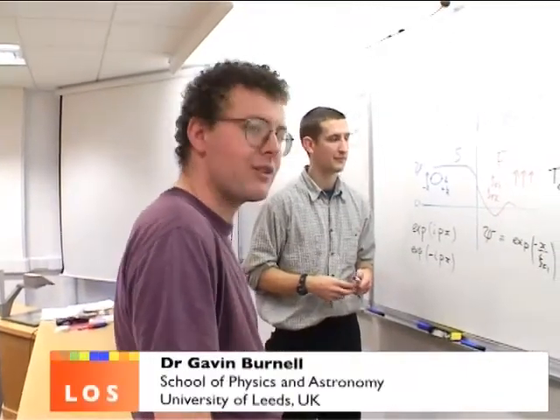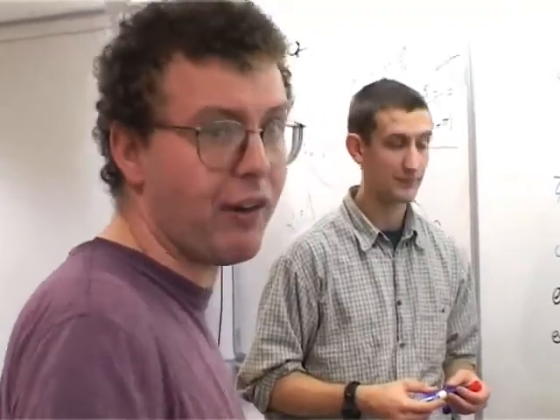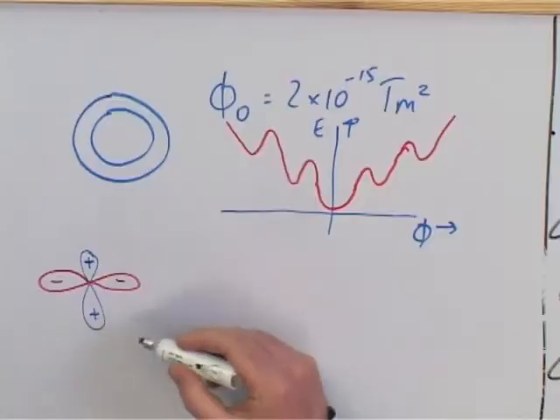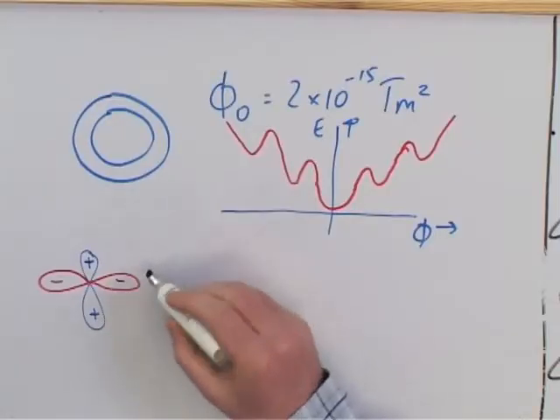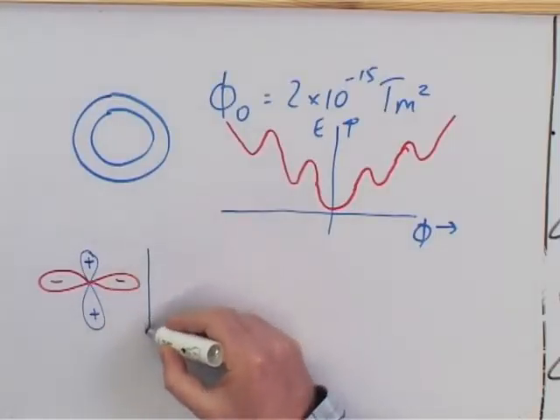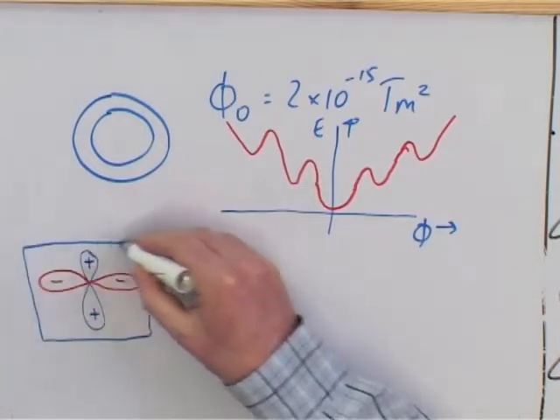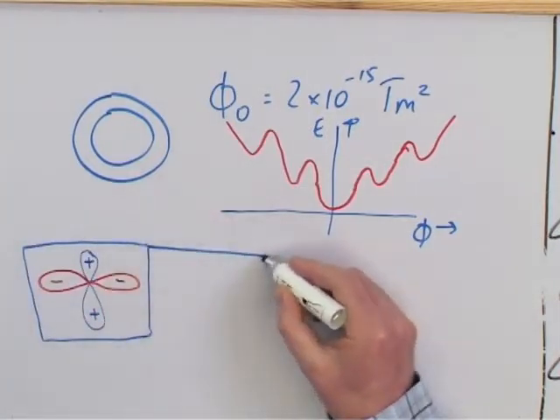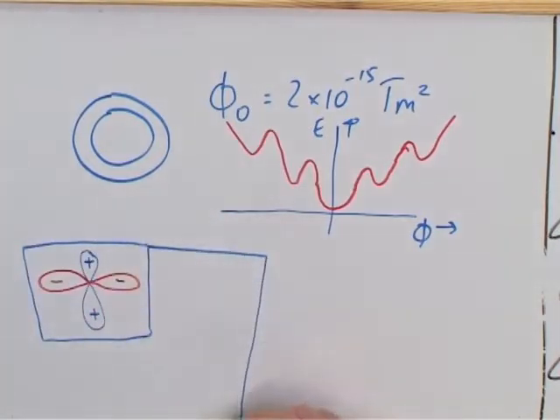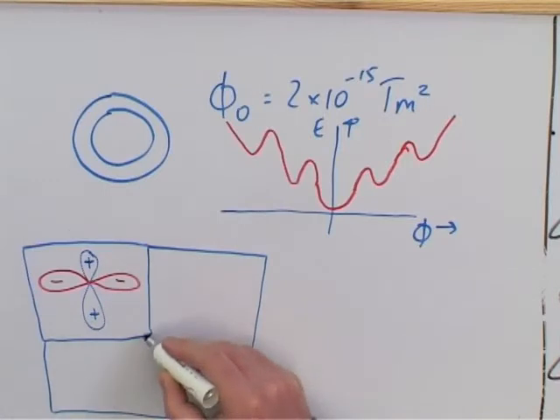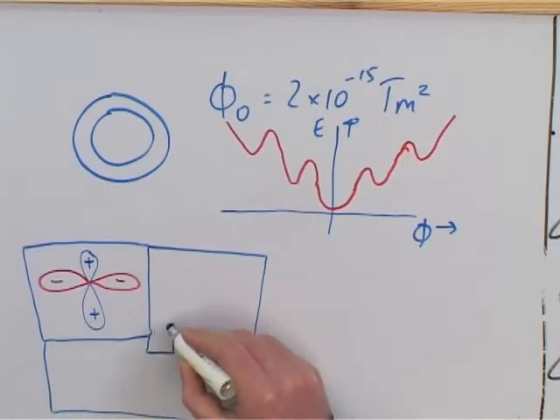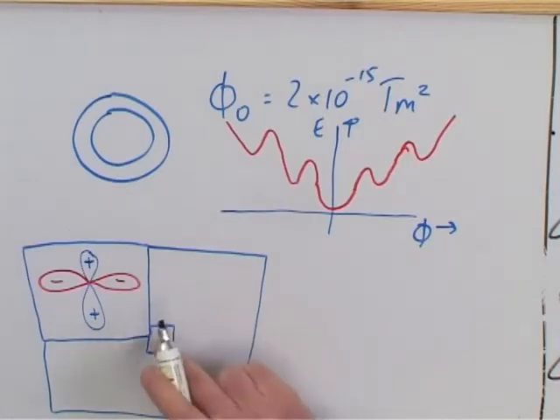So if you connect those two halves of the YBCO up, you end up with the same change, and therefore have to generate a loop of half a flux quantum. If you now make a ring and you connect such a high-temperature superconductor with a low-temperature superconductor, let's draw it like this, with a little hole inside.